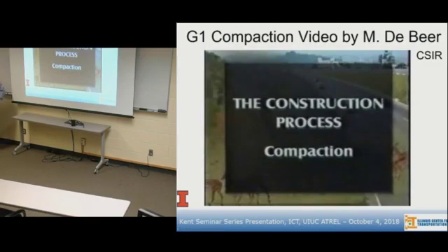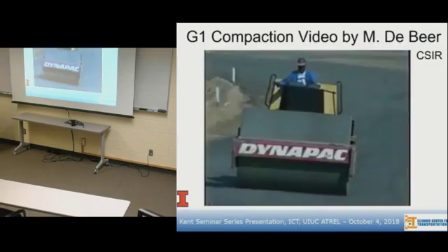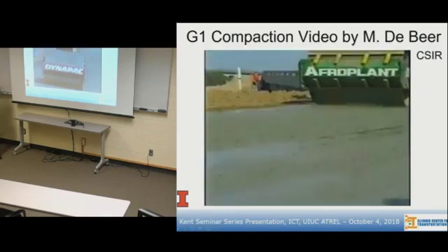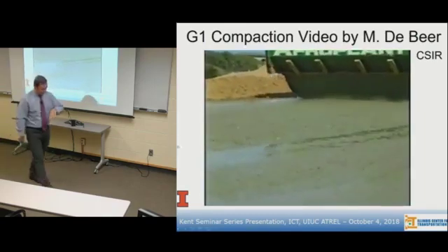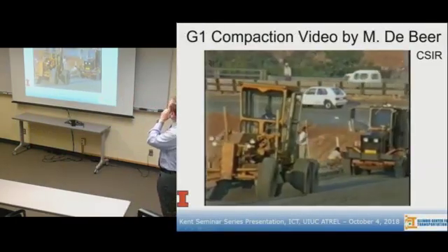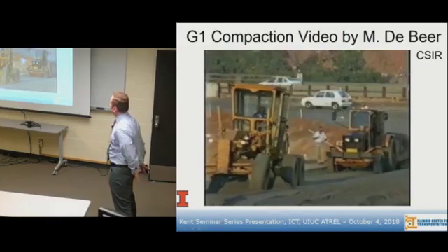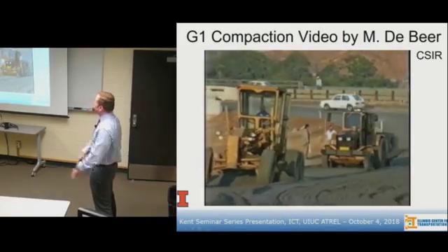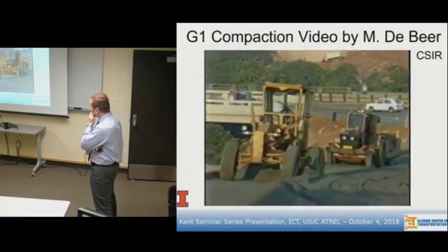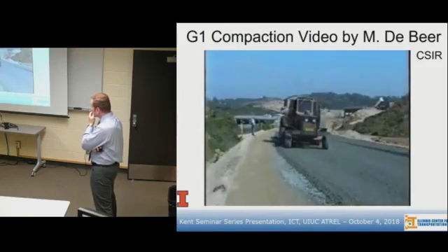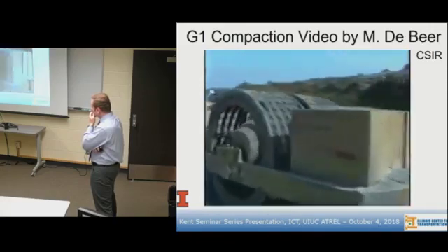The compaction process. The compaction process consists of firstly a standard compaction phase and secondly a particle interlocking or slushing phase. The standard compaction phase uses the customary method of compaction for gravel material to a minimum density level, which will allow the second phase to be executed successfully. The first phase of the compaction process should start immediately after the layer has been correctly shaped.